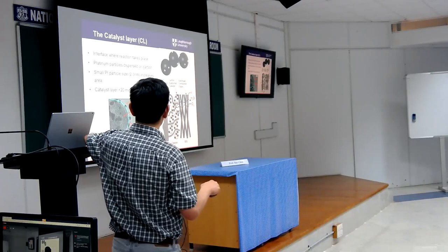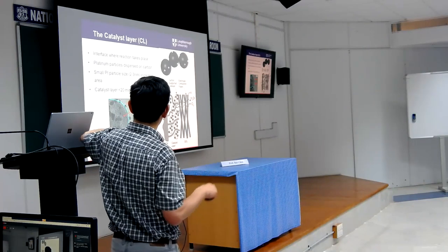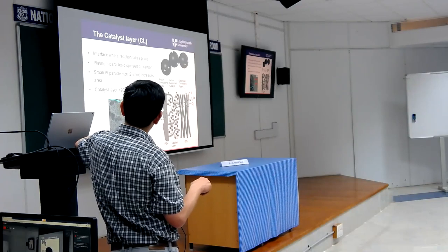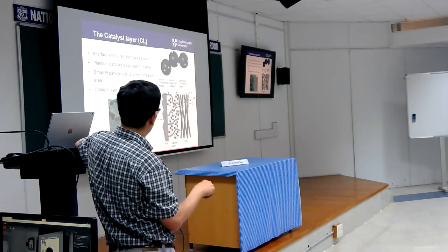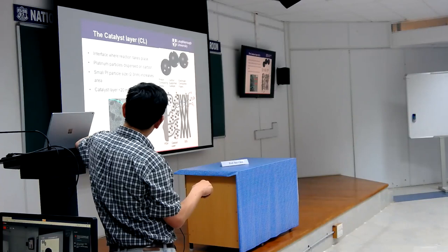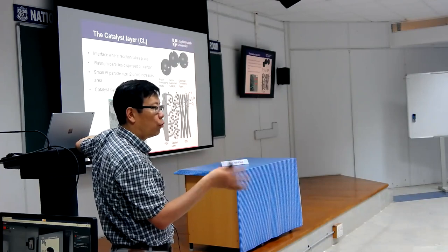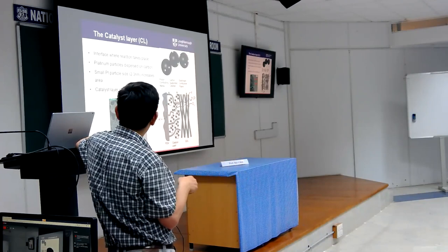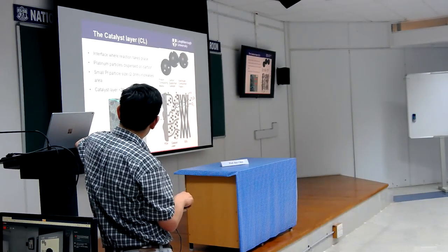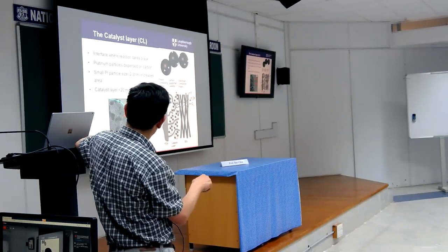Well, and so in this picture, if let's say that is 5 nanometers, overall it is about 20 nanometers in size. But the scale is 5 nanometers. What you can see is the black dots, and in this case the black dots really are the platinum. The platinum is about 1 or 2 nanometers in size, and it's evenly distributed. And the ball, basically the whole ball, is the carbon support. Basically, that's the substrate.